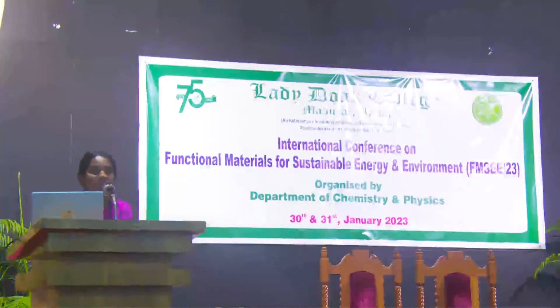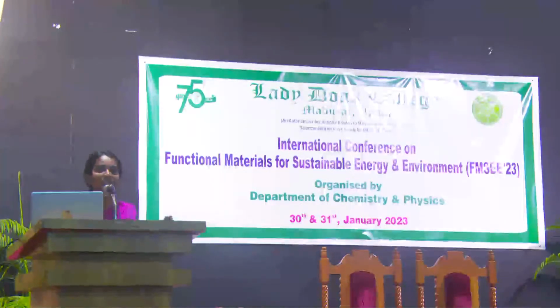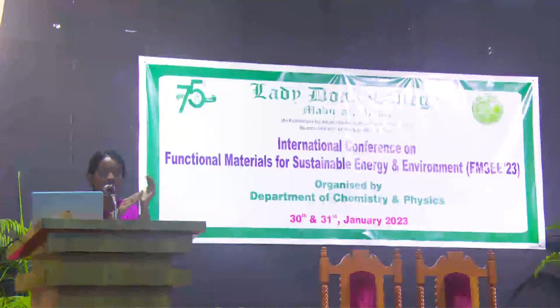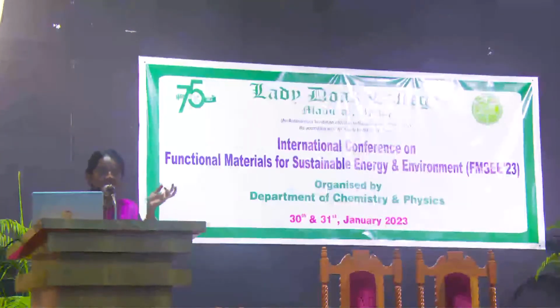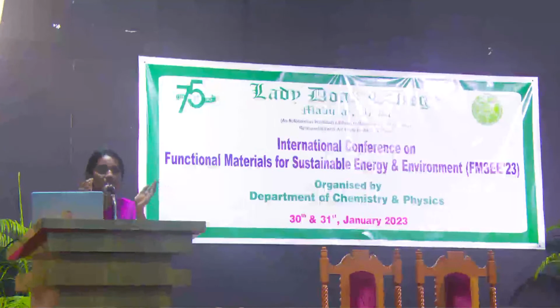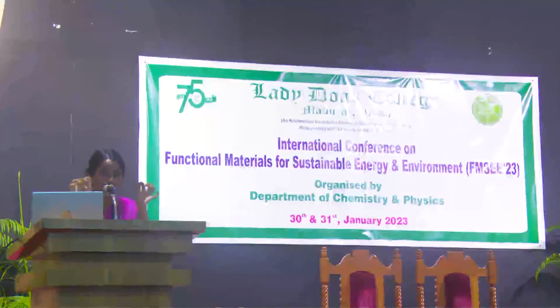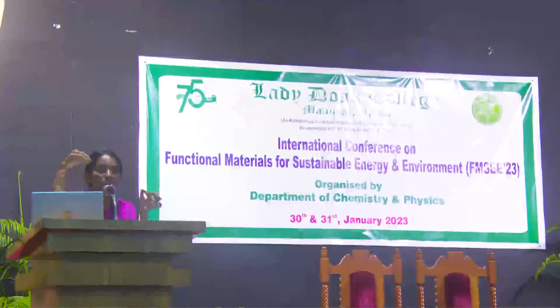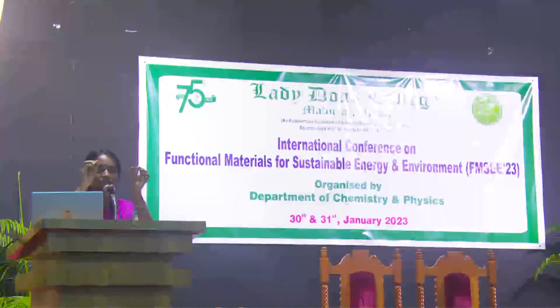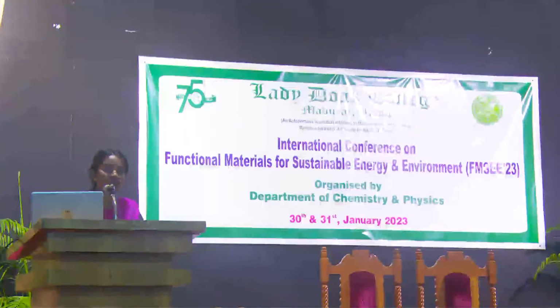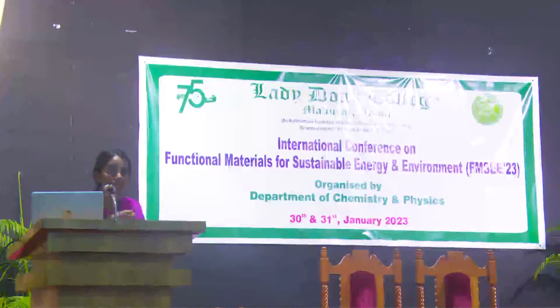What was the difficulty you faced during the characterization of your cathode material? The preparation. We have to oxidize all the graphite we chose as a precursor. In graphene oxide, the carboxylic groups should be present at the edges, not inside the medium. If we prepare graphene oxide, it should be a hydrophilic material. If it disperses inside the water, it means we prepared graphene oxide. So it should be highly soluble in water. Normally it's a very difficult process.